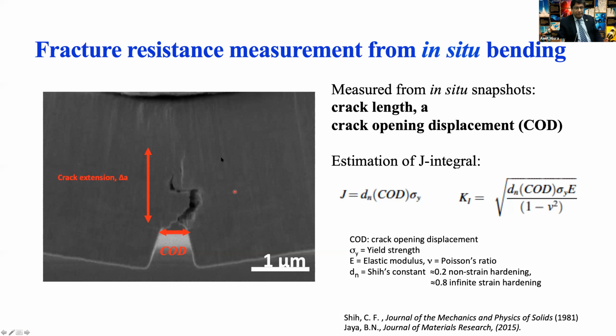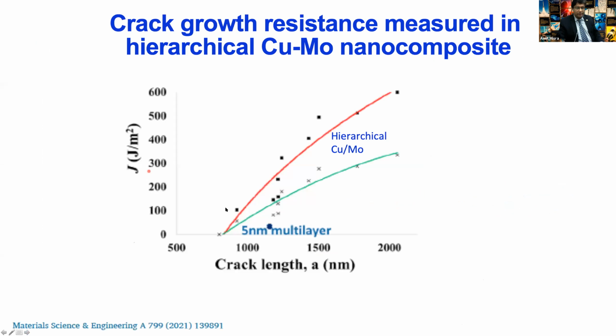We can also, there are expressions, these kinds of tests have been done for silicon microbeams, and there are expressions that others have derived where, because the test is done in situ, you can measure the crack opening displacement. And we know the yield strength, so we can estimate what the J integral will be, the strain energy release rate, which is maybe a better descriptor than the K1 because we have so much plasticity at the crack tip. So we are able to plot the J integral as a function of the crack length in this case.